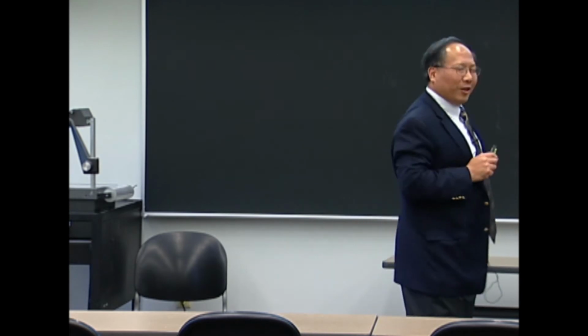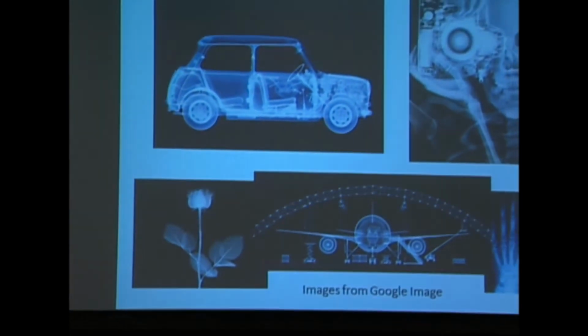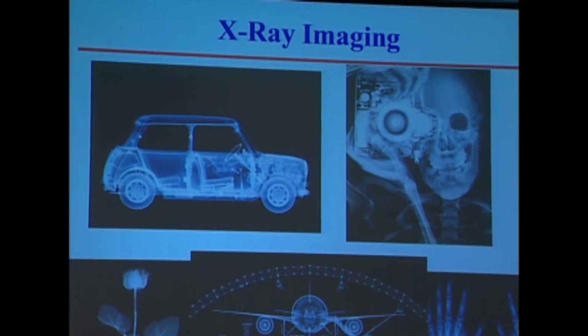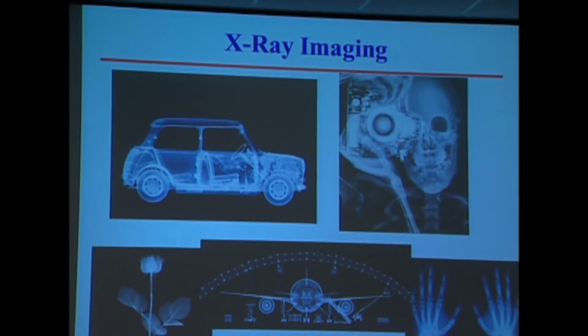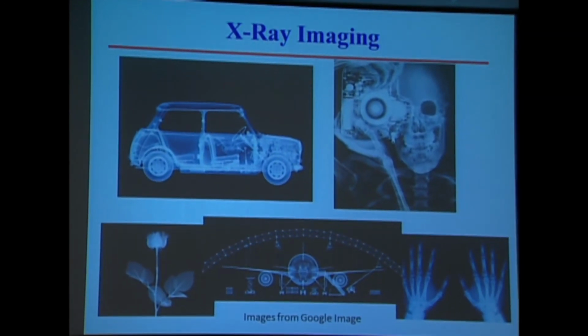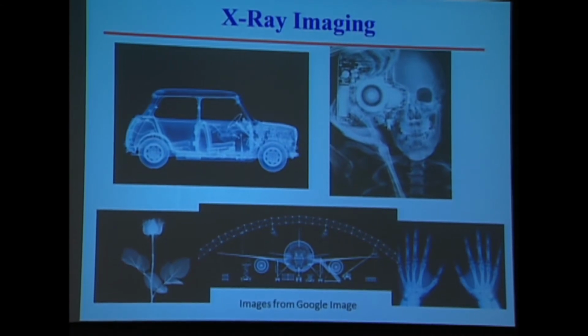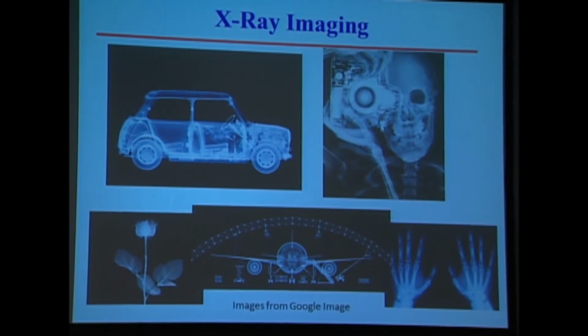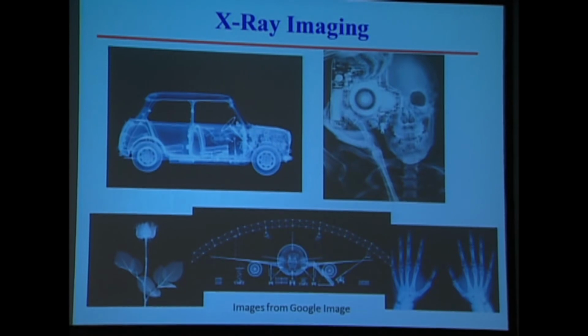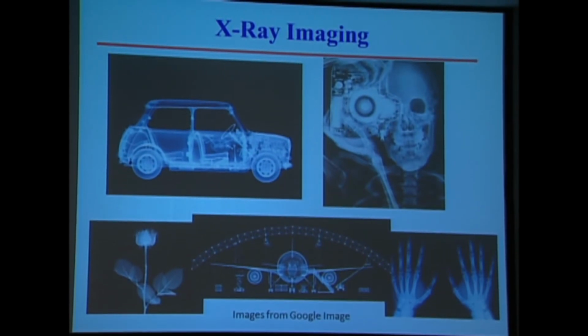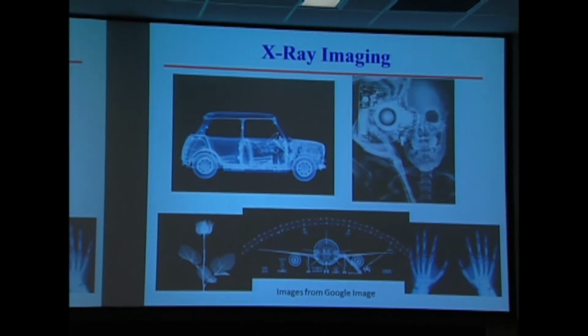So how do you see through things that are opaque? X-ray. So we were trying to use X-ray. And now, of course, this is not going to be the dental X-ray strength because the phenomenon is fast. I need a high-speed camera to record the failure process. So if your dentist is going to take a few seconds to take an X-ray of your tooth, in a few seconds I will run a few thousand experiments. So my X-ray needs to be much stronger.